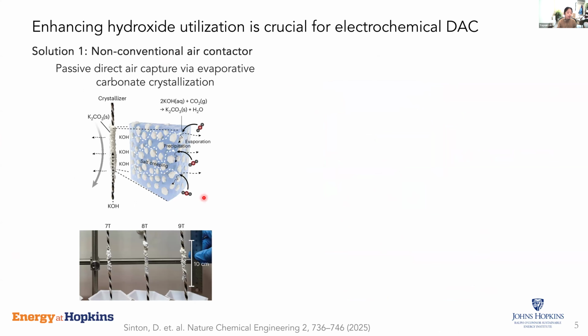And one of our colleagues, David Sinton at the University of Toronto, has recently proposed this really elegant idea of using a crystallizer as your air contactor. So instead of using a solution-based absorption method, this design uses a strand-like contactor and very concentrated KOH solution to form potassium carbonate crystals. And these crystals can be harvested as a solid and directly sent into an electrochemical reactor to get regenerated. So in this case, we are regenerating carbonate without regenerating hydroxide.